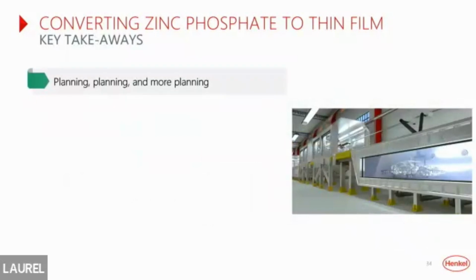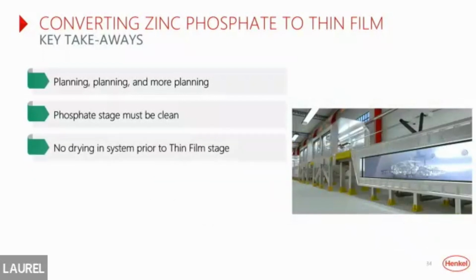So, key takeaways from this, and there are a couple, but some are more important than others. One of them is, again, planning, and more planning. The phosphate stage absolutely must be clean. We don't want any drying prior to the thin film stage. For many systems for the conversion, we've had to add additional risers in dwell zones to keep the unit wet. Rinse quickly after the thin film stage. If a knockoff riser is required, put it in.